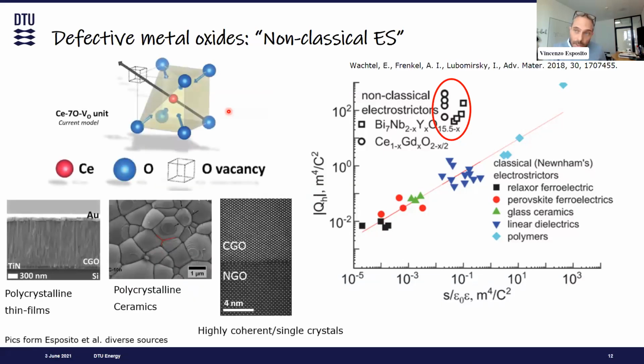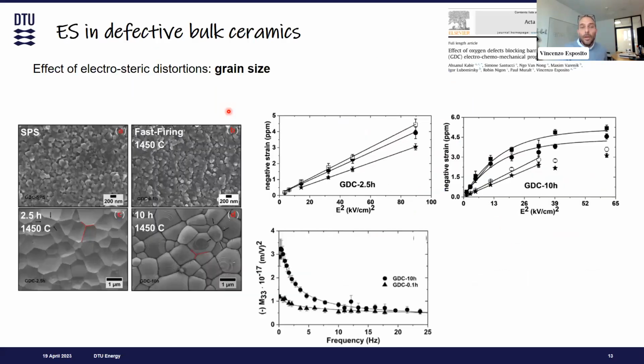What is also nice about this material is that this works in any possible ceramic configuration. So we go from polycrystalline to single oriented films, polycrystalline films. We still find this effect. And this is, I think, pretty important because piezoelectrics and only ferroelectrics have these properties after poling, right? And in ceramics, it is a pretty rare and precious property.